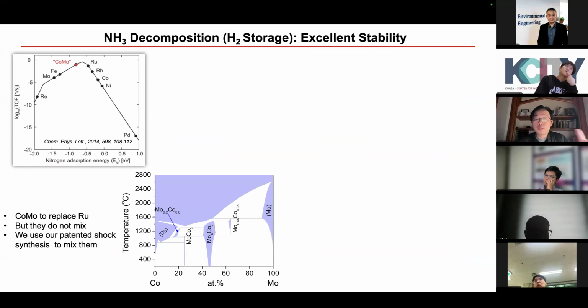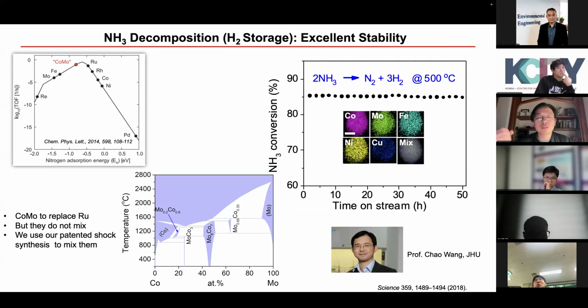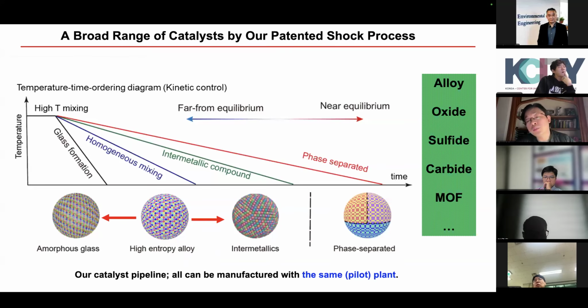And in this case, we're trying to design a cobalt and molybdenum catalyst. Cobalt and molybdenum are on the two sides of this volcano plot, right? So one is binding too strong, the other binding is too weak. If you have both of them, you will have to optimize the binding to basically maximize the performance. But if you look at the plot in the middle, you see that they don't mix at all. Right? So in this case, we mix them using high entropy, using the thermal shock, and we show excellent performance here. Right? So we also did some other catalytic reactions using ammonia oxidation, and we actually showed performance stable up to 1,000 hours. That, I think, is good enough for industry applications.